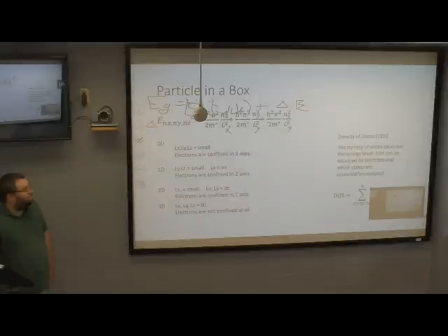And the correction due to confinement will be proportional to the equation that you're presenting. So if all the capital L's are equal to infinity, then this delta E will be equal to 0, and it will be the same as in the bulk. In this situation, only two of them are equal to infinity because we're looking at a 2D. What is m here? m is mass, and I don't know why there's a star there.